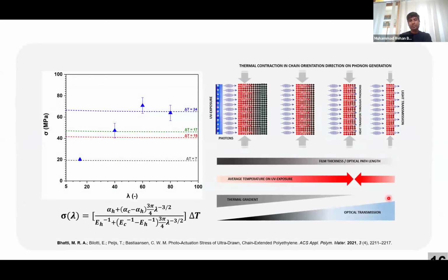So in the next phase, in order to understand and quantify this behavior, the influence of solid state drawing on the photoactuation stress of oriented semicrystalline polymer was explored theoretically. A semi-empirical model was created in which the factors affecting the actuation stress were explored, for example, the negative coefficient of thermal expansion, Young's modulus, and the difference between the temperature before and after illuminating. The result was surprising: the decrease in the negative coefficient of thermal expansion is actually counterbalancing the effect of increasing Young's modulus. And the only factor that comes into action is the change in the temperature.